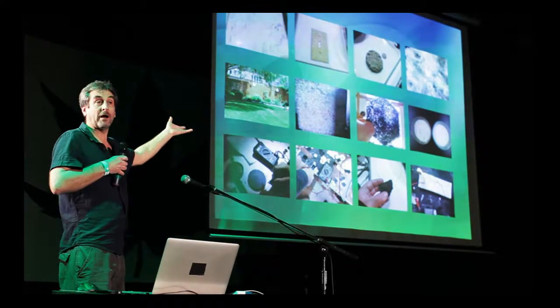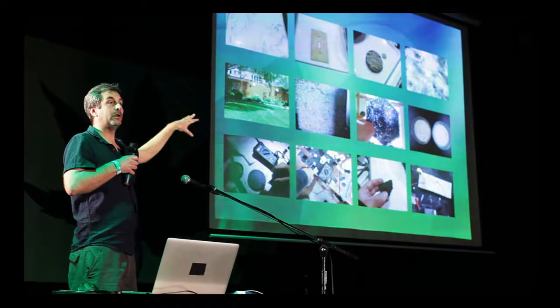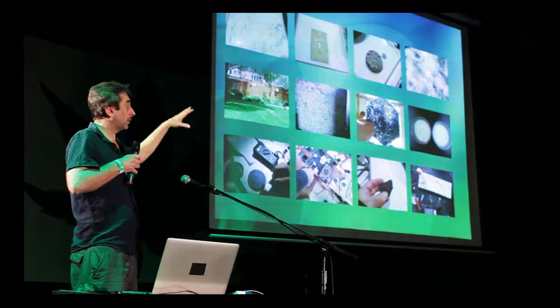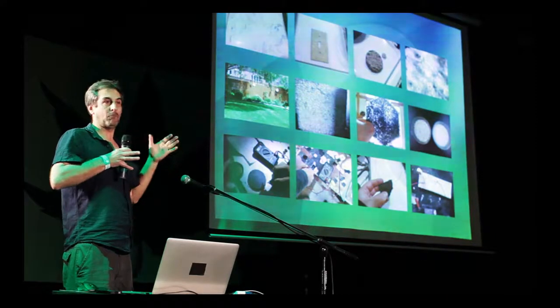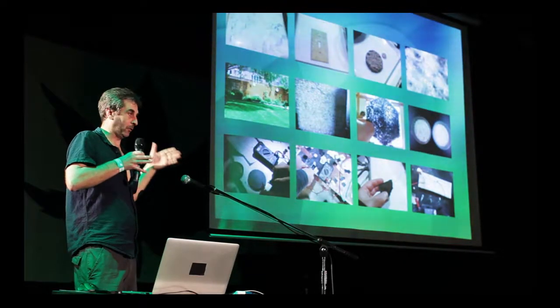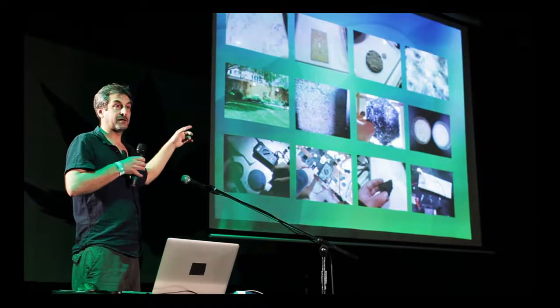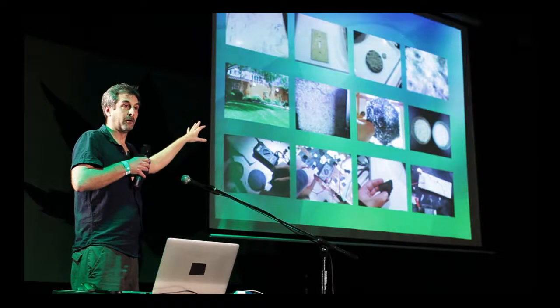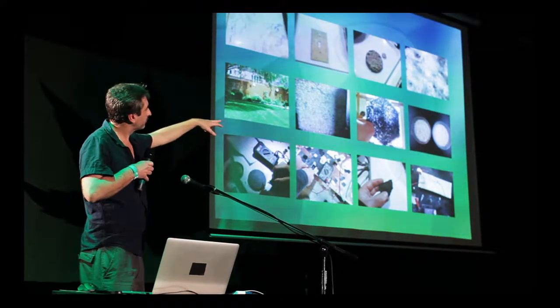Next is hempcrete — I've been designing a block and have made improvements to the recipe. This block is only seven inches thick, whereas traditional hempcrete or lime-hemp walling systems are about twelve inches thick — thirty centimeters. At just seven inches, I still maintain an R24 insulation value.